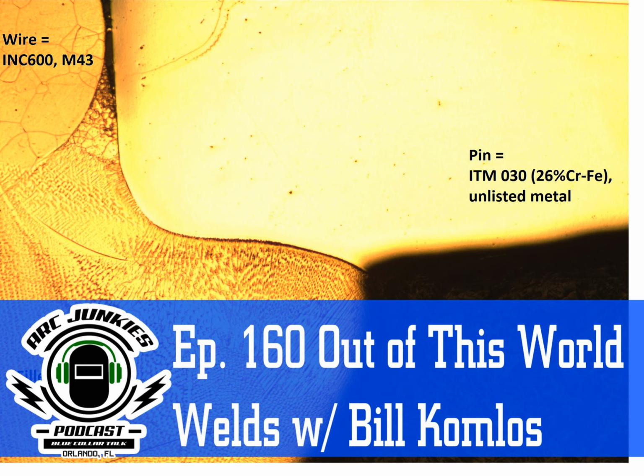Yeah, no, you just preheat the heck out of it because the carbon equivalent is up there around 50 or 60. You can't believe it's going to stick. But again, a nice low hydrogen rod, and sometimes for an indirect butt, you can often even just use a 70 class if you're using an angle iron for your splice strip, because you're not going to get full strength out of that. It's going to be your angle iron or your plate, whatever you've used to set the butt joint on. That's your weakest spot. So you could weld with a 70 class electrode all day. It's only when you've got a square butt joint that you're really going to generate the strength of the base metal for a pull test.